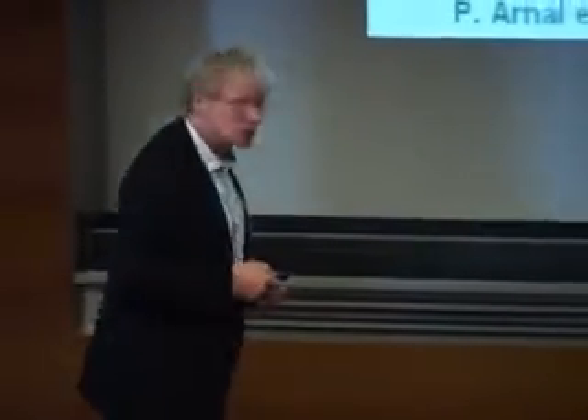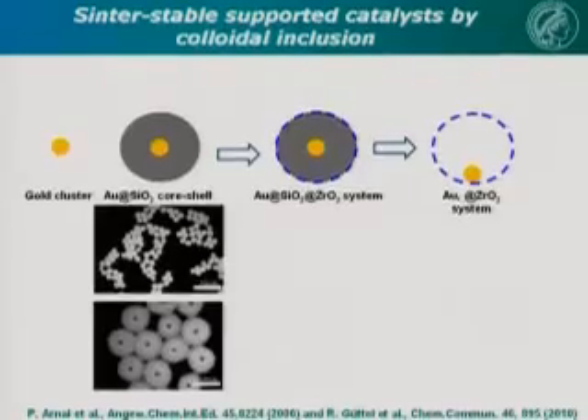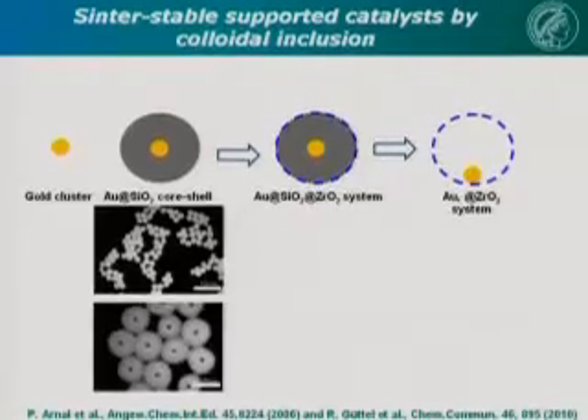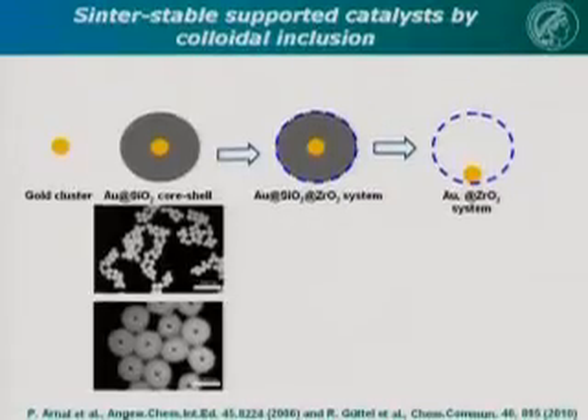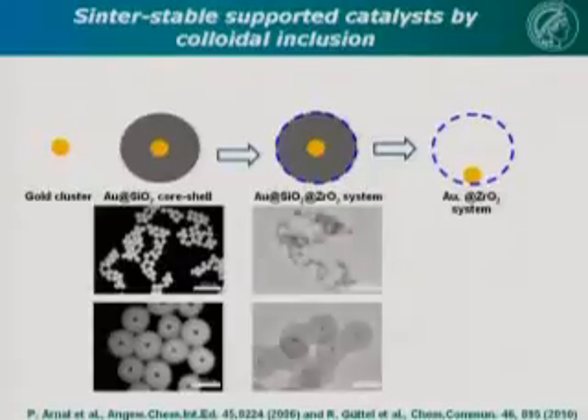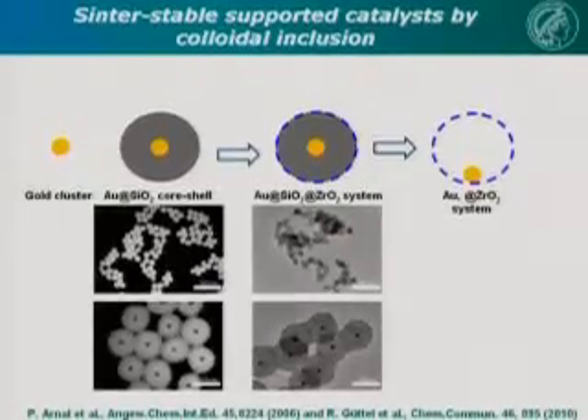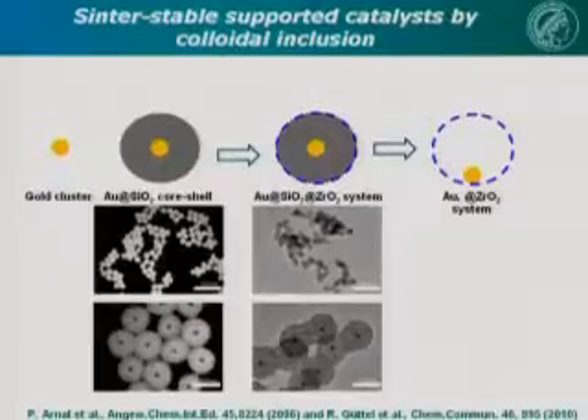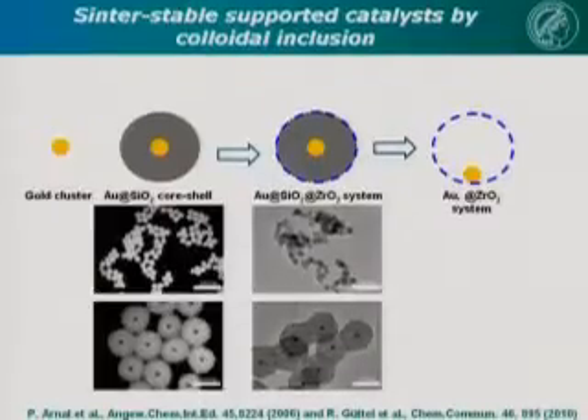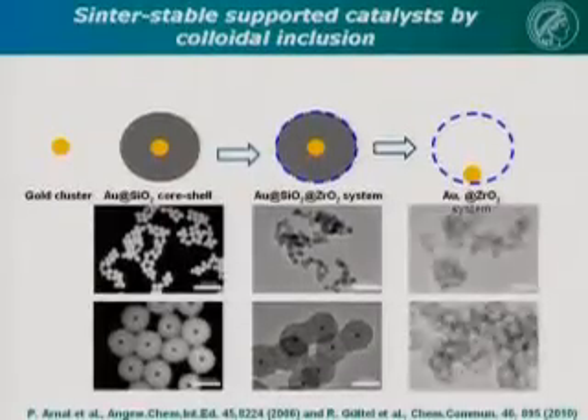This is a nice cartoon. You can draw many nice cartoons in this field, but you should prove that you have what you claim you have. You can see that quite nicely with electron microscopy. Here is the gold particle in the center of the silica sphere. Looks a little bit like fried eggs with the gold in the center. You coat with the zirconia, then it gets a little bit gritty on the surface. This is the porous zirconia shell, let's say 10 nanometer, 20 nanometer thick. You notice gold is still in the center here because the silica keeps it there. And then you leach the silica, and you get this.